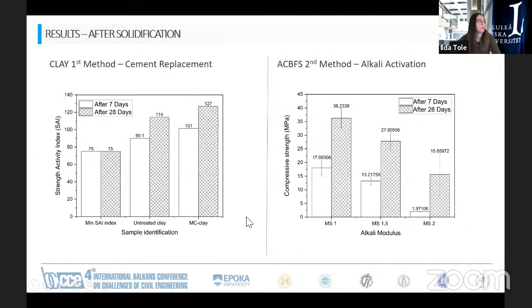And for the cement replacement, the first method, in the comparison of the strength activity index, we had an absolutely good result with the treated clay going over 127%, where the minimum required was 75. However, this was not enough. For that, we chose to do the Frattini test, or chemical analysis, because we already know that after grinding the material was fine, so a filler effect can contribute to the increase of the strength values. Another comparison was done with the alkali activated material, and we had a nicely comparable result of the compressive strength with the more utilized ground granulated blast furnace slag.